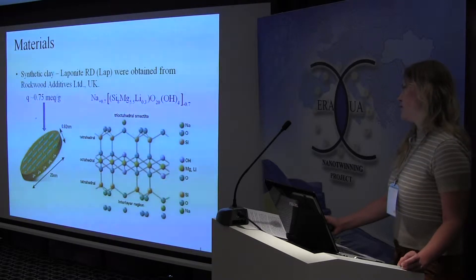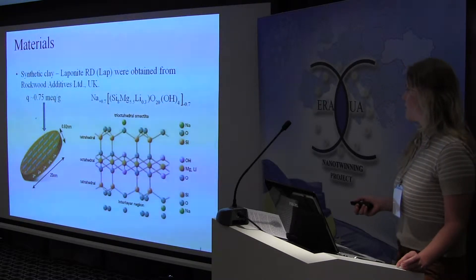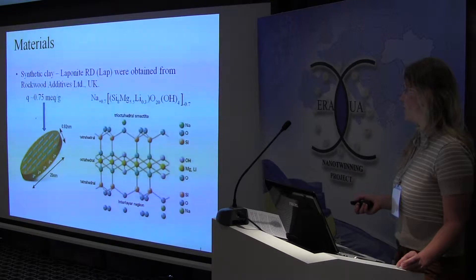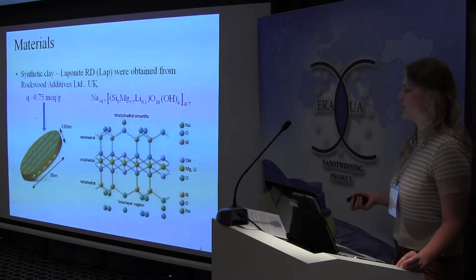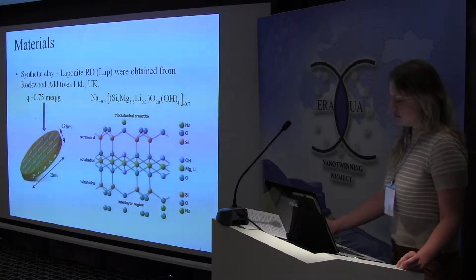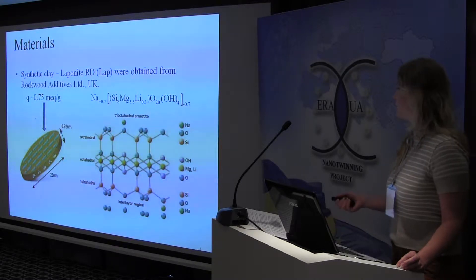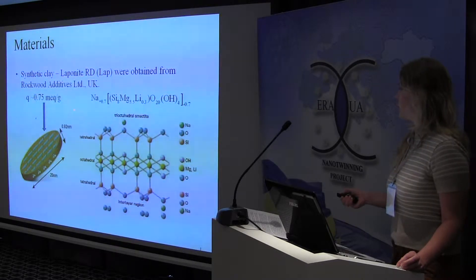Their surface is charged heterogeneously. The faces have a constant negative charge, while the charge of their edges is pH-dependent and positive in acidic medium. The negative surface charge of laponite is counterbalanced by positive sodium ions.